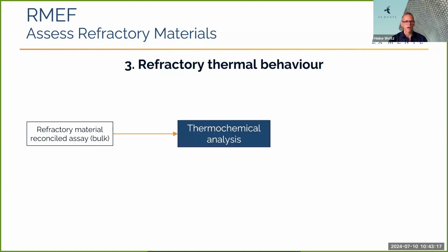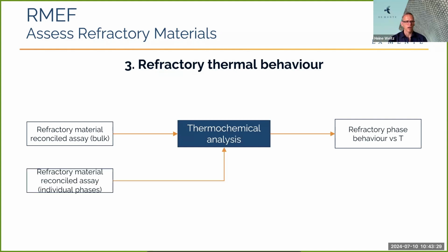Okay, so then we look at the refractory material on its own, how it behaves as a function of temperature. So we start off with the refractory material reconciled assay that I showed on the previous slide. And on that, we can perform a thermochemical analysis and simply look at how the refractory material behaves as a function of temperature. At what point will it start to melt? And again, as I said, we also need to look at the individual phases to make sure that we don't have a phase in the refractory material that would melt prematurely.